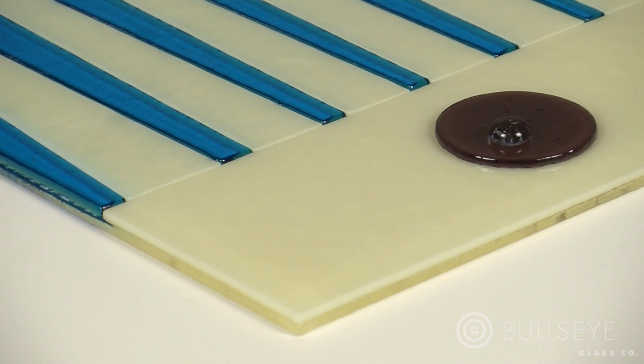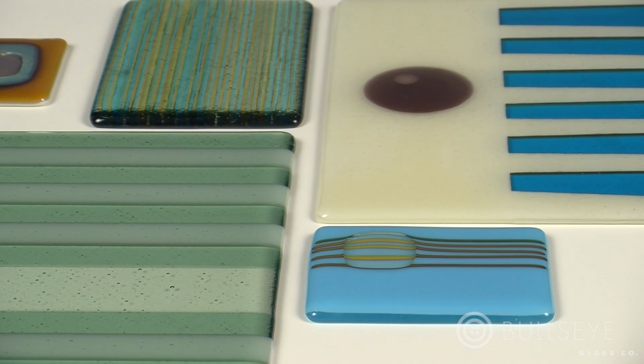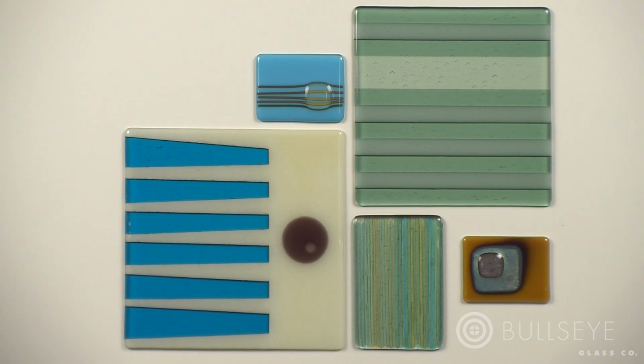As temperatures increase, any glasses added to the top surface will soften and flatten more and more. At 1425 degrees, surface additions are much smoother and glossier, but there is still some relief on the surface. Now that you understand the 6mm rule, design up and design down, managing bubbles, and basic firing cycles, you are off to a good start in making successful fused projects using Bullseye glass.